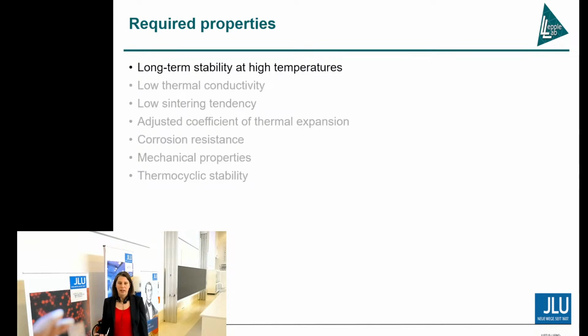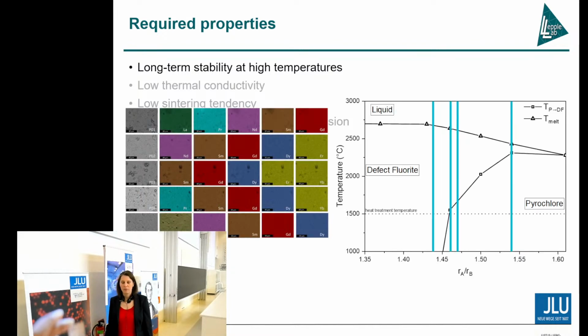thermocyclic stability. And for the high entropy oxides which we investigated, we actually can see here a material with a homogeneous distribution of the elements in the microstructure. On the right side, you can see a phase diagram where we have the temperature plotted against the radius ratio of the rare earth element, in this case divided by the radius of zirconium. And so you can see that, depending on the phase we have, so either defect fluorite or pyrochlore structure, we have transition temperatures above 1500 degrees centigrade. And that's the temperature where also the materials are synthesized. So they are stable up to very high temperatures.